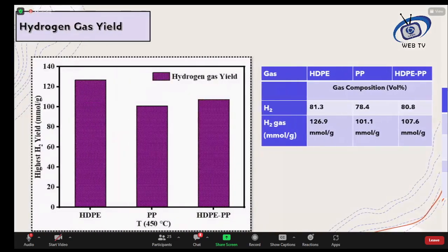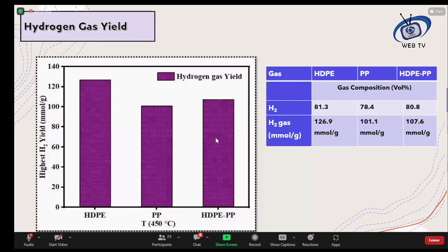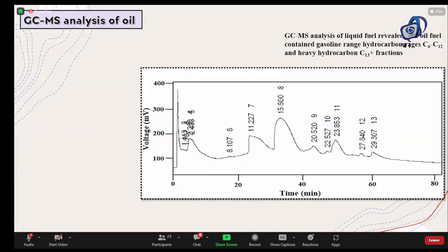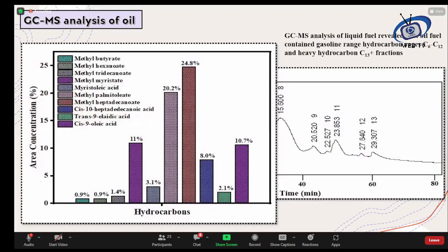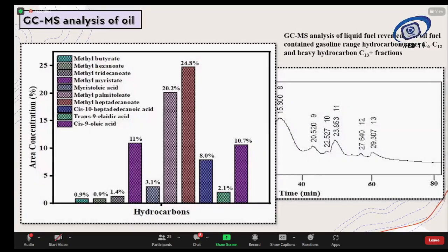Then we conducted the GCMS analysis of the liquid product to check what carbon chains are present in the product. After that, we found that the liquid product contained gasoline-range hydrocarbons ranging from carbon 6 to carbon 12 chain, and some heavy carbons having carbon chain 13 and higher. So these are the different compounds we find through GCMS analysis in the product.